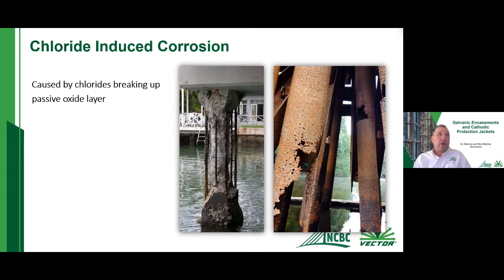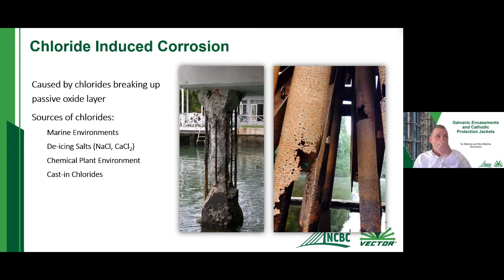So chloride-induced corrosion, here are a few pictures of them. Obviously, it breaks up that passive oxide layer, like I mentioned. There are a number of sources for these chlorides. The marine environment that we're going to be talking about here is a big one for us, and there are a number of other areas you can get chlorides from as well. One of the things to think about is that chlorides are never actually consumed in this process, so they're always there to continue that corrosion cycle, regardless.